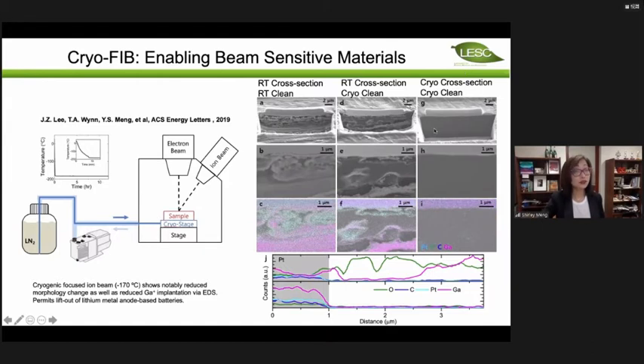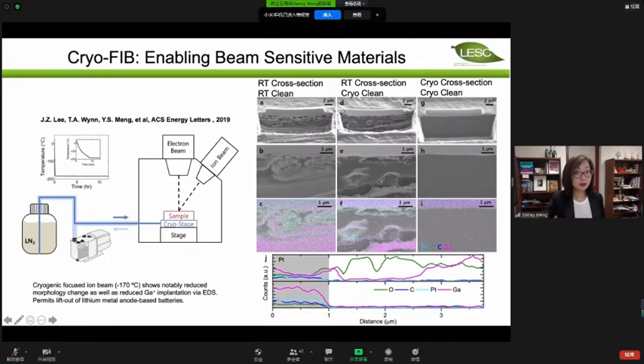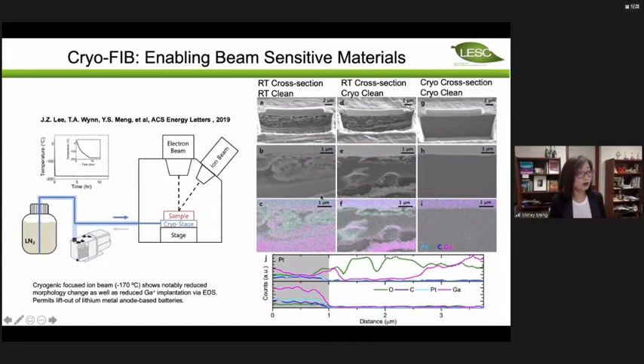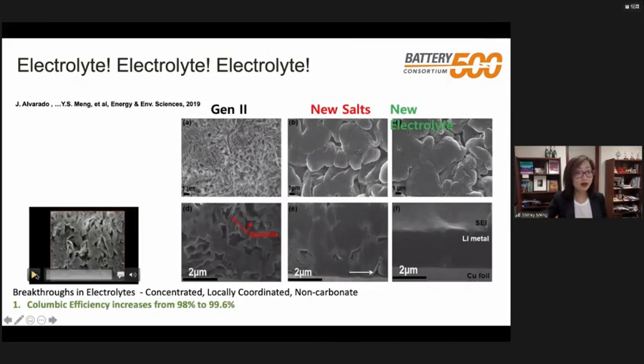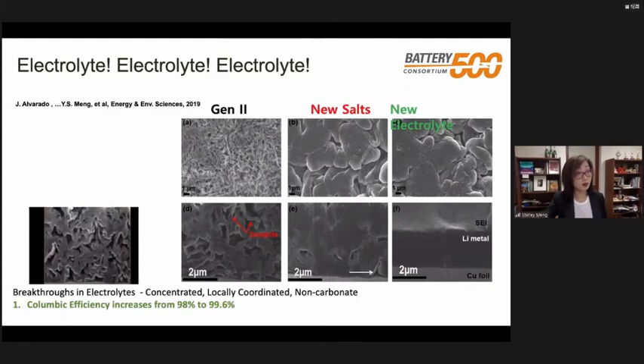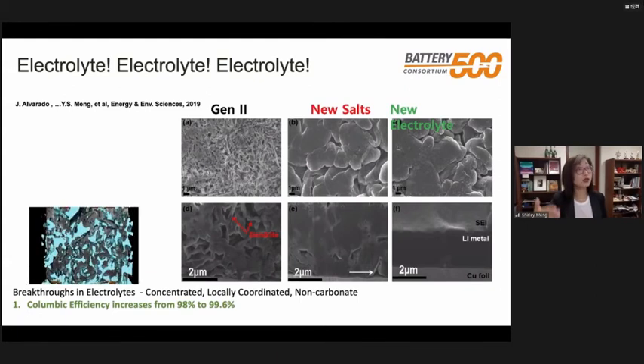If you actually use cryogenic conditions, the kinetics of the interaction will be dramatically reduced, and that's where you can get a quite clean surface of the lithium metal. This lithium metal is of course just a metal sheet, so it is supposed to be dense and very smooth and nice looking. Now, why is this tool so important? Because electrochemically deposited lithium does have a lot of pores and tortuosity. So if your tool already interfered with the lithium, you cannot observe lithium very well. That's a very easy logic to follow, right? So with this advanced tool, we can now cut lithium slice by slice in the FIB, and we can do three-dimensional reconstruction of electrochemically deposited lithium.